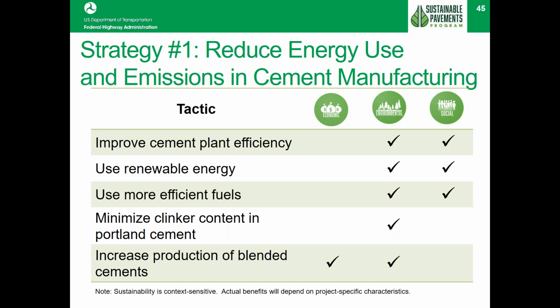The cement production itself is inherently aggressive in terms of producing greenhouse gases, because about 50% of greenhouse gas emissions from cement production is actually inherent to the production itself, because the process involves converting limestone into lime, and limestone, which is calcium carbonate, producing lime produces carbon dioxide as a byproduct, and that amounts to about 50% of greenhouse gas produced in the production. And there's nothing we can do to improve that. So as long as we use cement, this is an inherent part of using that product.